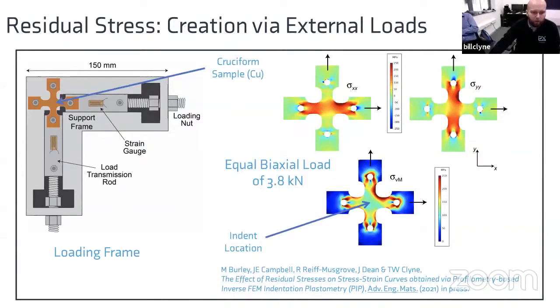So previous papers had stated that they used the applied load from this kind of setup divided by the area of the sample in the cross section here to give you the residual stress in the center of the cruciform. Unfortunately, that's not quite right. There are two things that you have to consider as well.